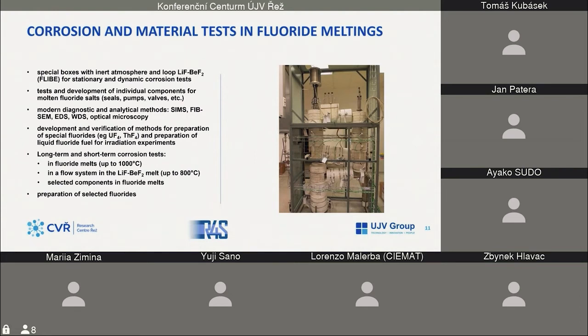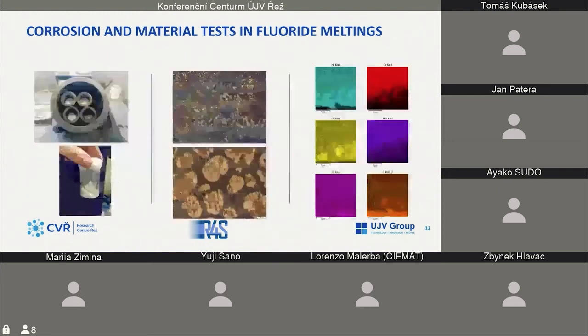Thanks to modern diagnostic and analytical methods like SIMS, FIB-SEM, EDS, WDS, and other optical microscopy, again, we are able to characterize the samples very deeply before and after the experiment, so we obtain very interesting results from this research.